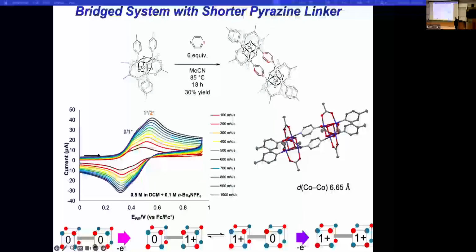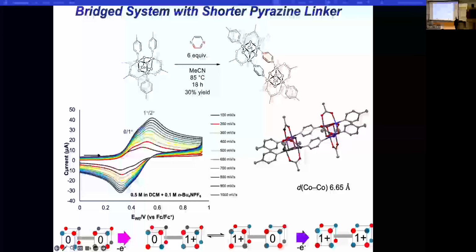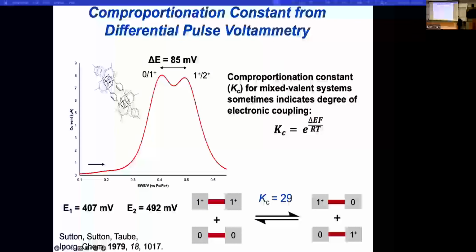Now you can see two closely spaced oxidation events for oxidation of the cluster. And we attribute that to a first and second oxidation. And the way that would go is indicated by the cartoons shown down here. Not a lot of separation. So that means there's not a lot of coupling in that system.